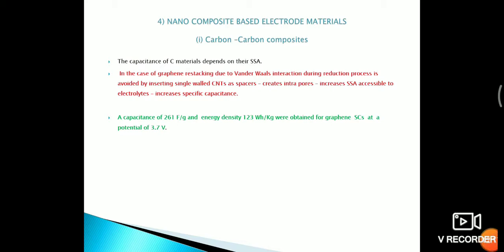Next is nanocomposite based electrode materials. First one is carbon-carbon composite. The capacitance of carbon materials depends on their specific surface area. In the case of graphene, restacking due to van der Waals interaction during the reduction process is avoided by inserting single-walled CNTs as spacers. This creates intrapores within them and it increases the specific surface area that is accessible to the electrolyte. That increases the specific capacitance also.